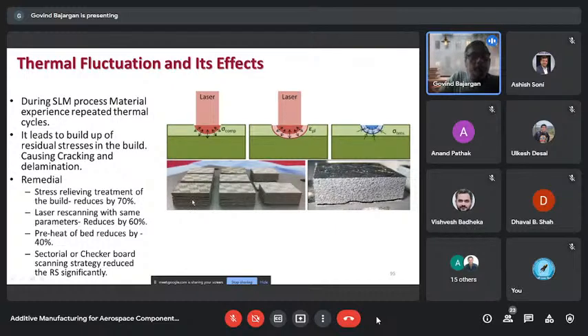So many of the stress relieving solutions are available: a stress relieving treatment reduces residual stresses by 70%. Laser rescanning is another technique which is employed to reduce the residual stresses. Preheat of the bed, as I told earlier, gives 40%, and there are scanning strategies also that you can change to reduce the residual stresses.